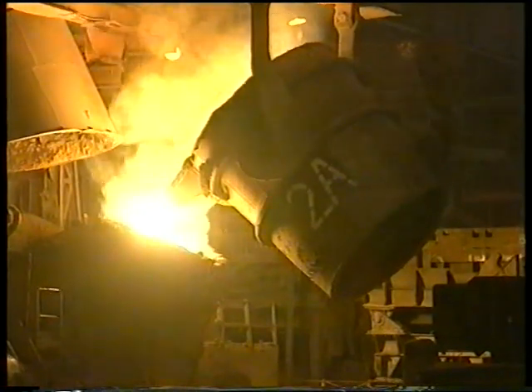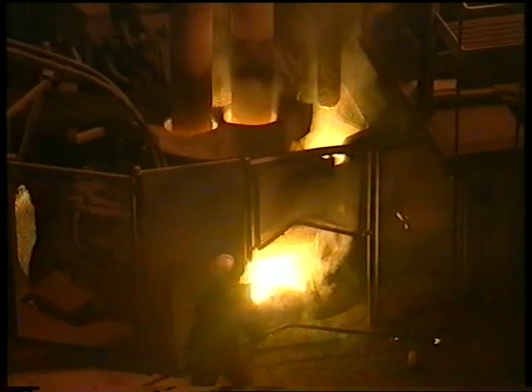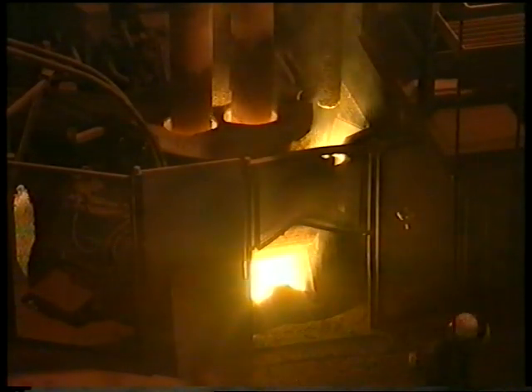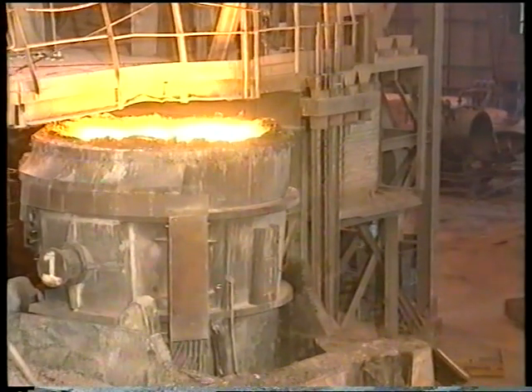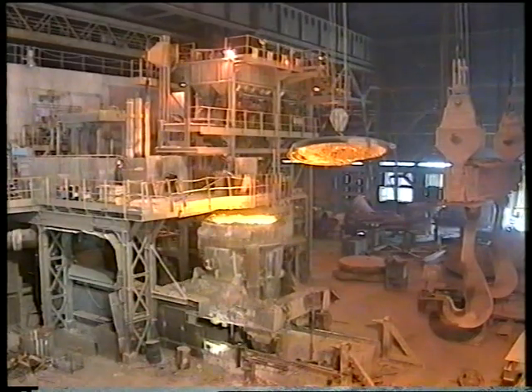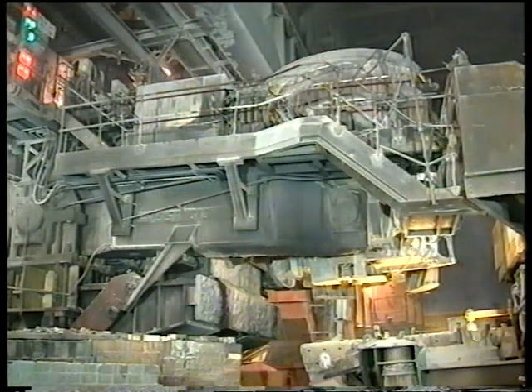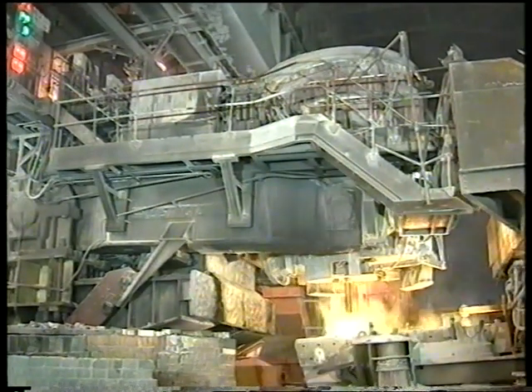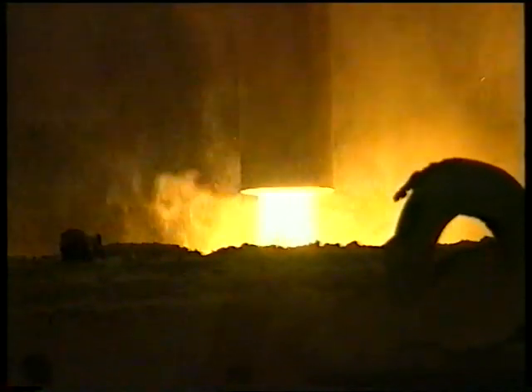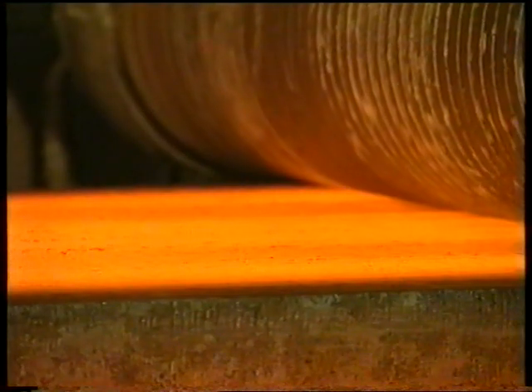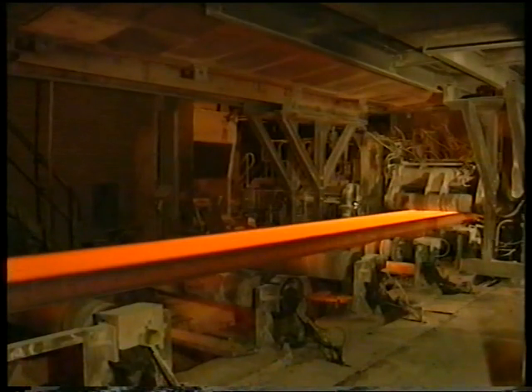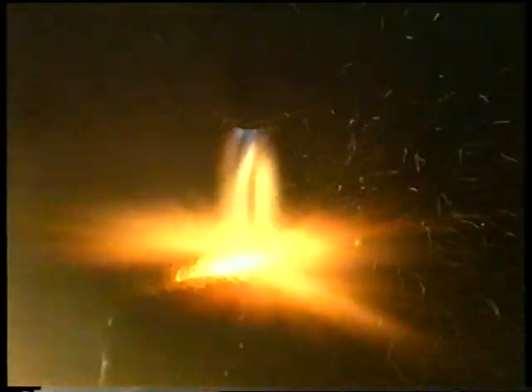The molten metal is then transferred to the argon-oxygen decarburization vessel, known as the AOD, where the level of carbon is reduced. Further refining takes place in the ladle arc furnace, where small quantities of ferroalloys are added to achieve very tight analytical tolerances. Finally, the liquid steel is transferred to the continuous caster. As the steel solidifies, it's monitored by computer to the point where it's cut into slabs. These are up to 15 meters in length and 300 millimeters thick.